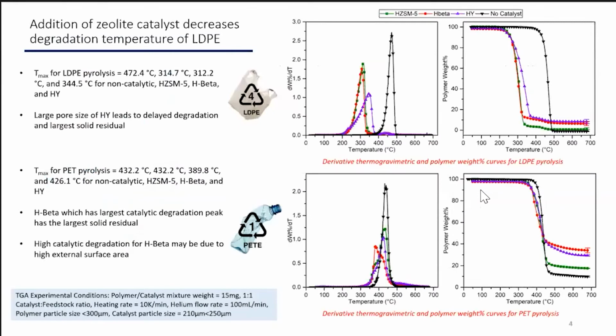And so the first results of this work I want to show you is the results from the TGA. So on the top, we can see the TGA curve for LDPE. And what we are able to see is that the addition of the catalyst greatly decreases the decomposition temperature of this LDPE. And when we look down below for the PET, what we see is that adding the catalyst does not decrease the decomposition temperature nearly as much.